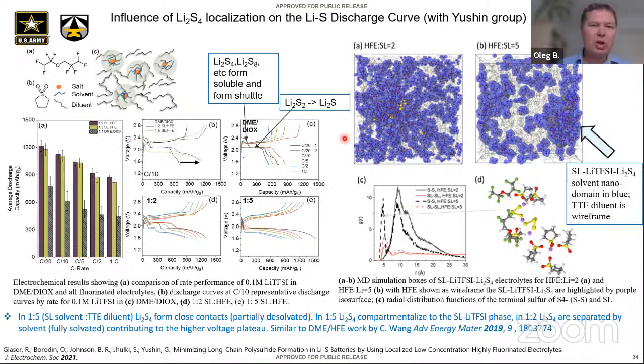One of the big problems is that longer polysulfides form, and if we take a classical DME, dioxolane, lithium TFSI system, this higher plateau is typically formed by longer polysulfides, while the lower plateau is described as Li2S2 to Li2S conversion. So now the question is what about this plateau, due to solvated species, which have been a lot of work done and identified: can we get rid of it? Because if we remove the solvated species and reduce their solubilities, there's going to be less shuttle in the lithium sulfur cells.